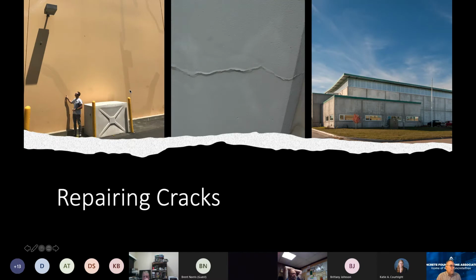On the left-hand side, you've got some dramatic concrete cracks. Now, accentuating the cracks is the fact that they decided to try to patch it and then repaint it. They used the same color paint, but it hasn't bleached out to match what the original paint was. And so these cracks are just blowing up aesthetically. But you've got these cracks that are diagonally moving up along the bottom of that panel.